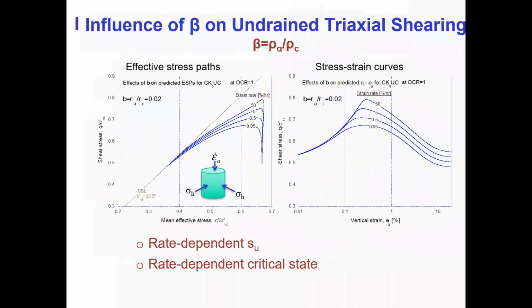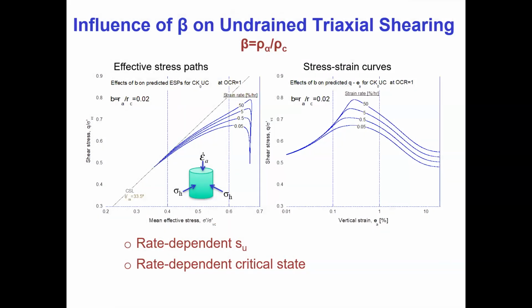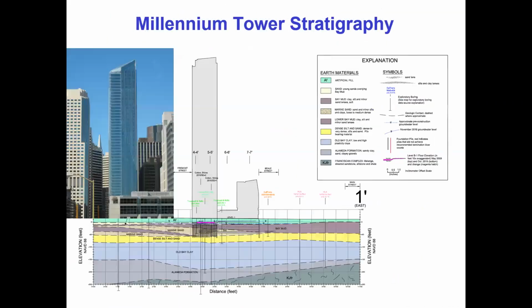We can repeat this by changing the beta value, and we shift not just the peak strength, but also the critical state. In other words, critical state is strain rate dependent, which probably wouldn't surprise the people who first worked on this, people like Steve Poulos and Gonzalo Castro. So what I've shown you in A versus B in one-dimensional compression has equal significance when it comes to undrained shear response in clays. And this has been very important for us because we can now tackle really quite complex problems.